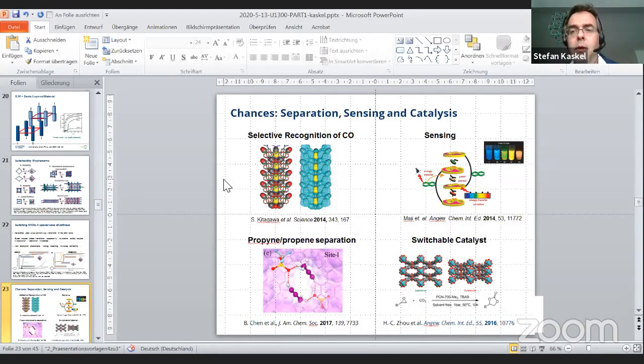Yes, so from what I think is in the current state of the art present, we can say that the larger the volume change in the crystal, the higher is the stress, and this induces the cracking of the crystal and fractionation, which does not mean that the MOF is destroyed, but it just means that the crystals are fractionated into a domain structure. We also reported a paper on this comparing 3 or 4 different archetypical MOFs with 100 cycles. And for example, MIL53, which has a lower volume change, can be cycled many, many times without cracking, while other MOFs, which have a huge volume change, can show the cracking.